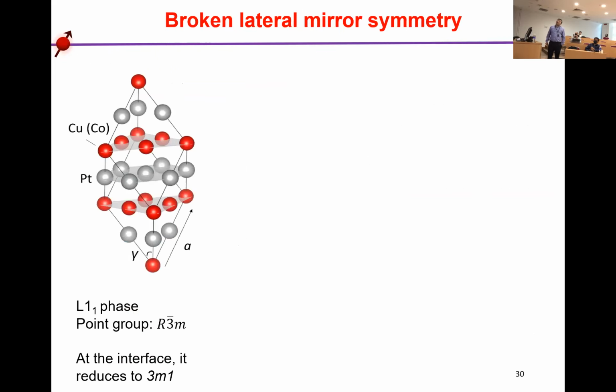And furthermore, we demonstrate other low symmetry materials, cobalt-Pt and copper-Pt, which have L1_1 structures. This structure has a one-atom layer of copper or cobalt and a one-atom layer of Pt along the [111] direction. Actually the space group is R-3m, but at the interface, if we make the double layers, the interface symmetry is reduced to 3m1.